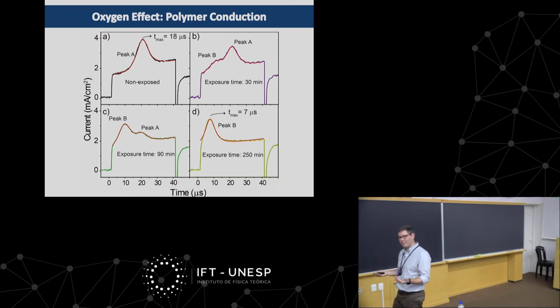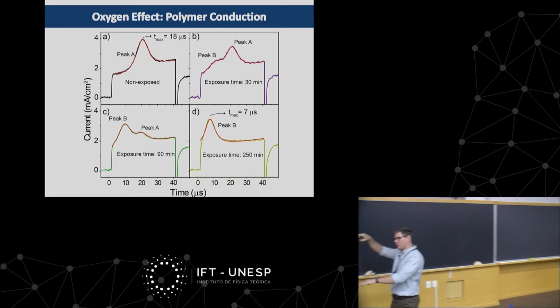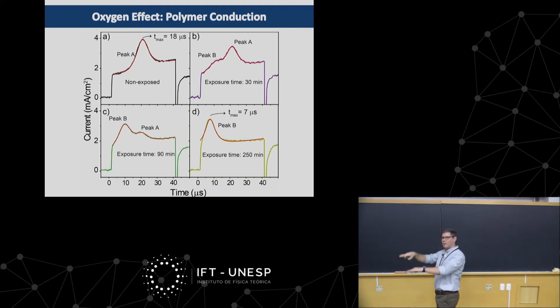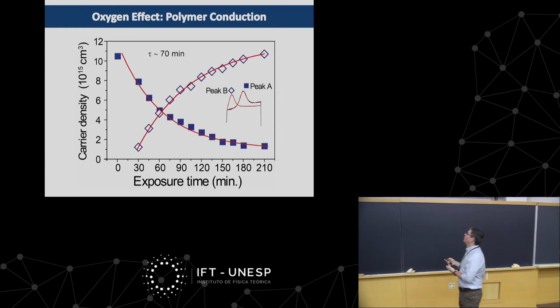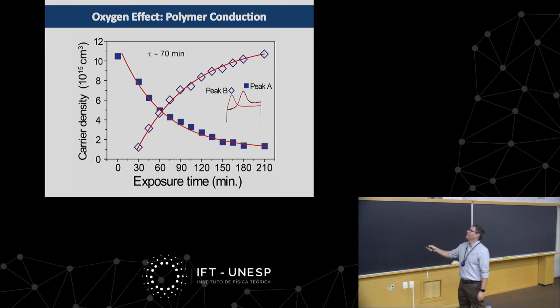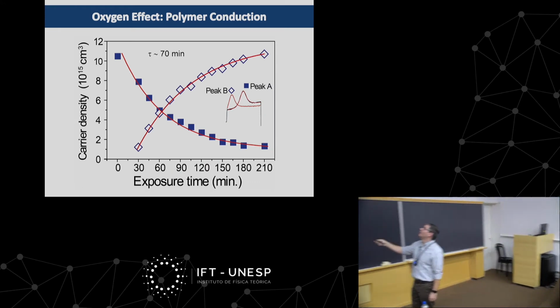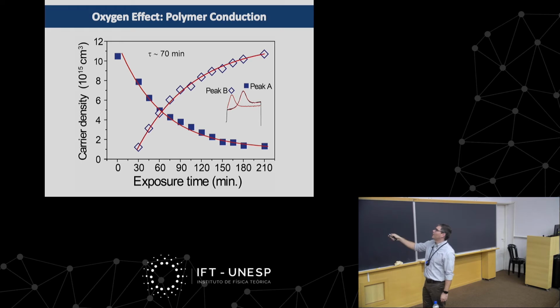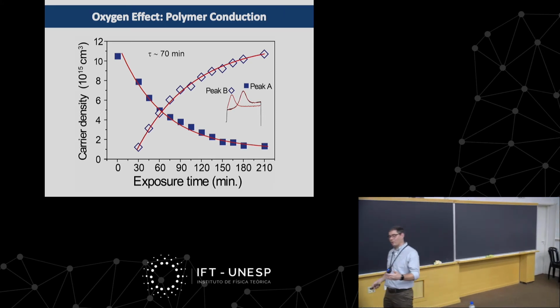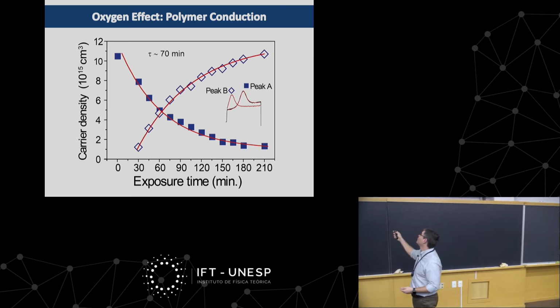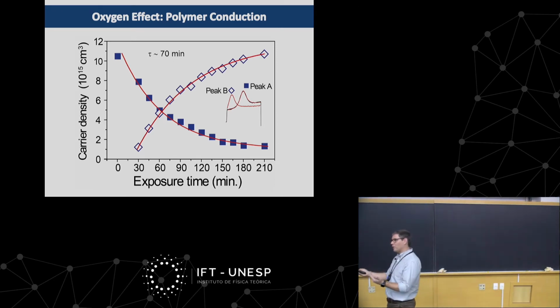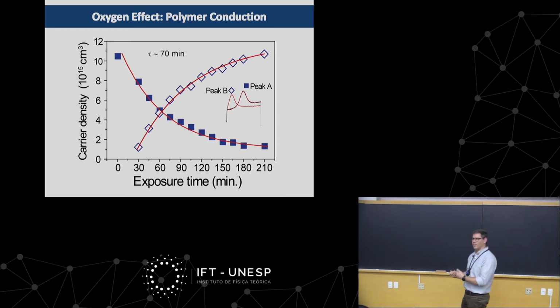And you see that the rate seems to be very similar. One actually decays at the same rate that the other one appears. And we actually measure the rate. So this is the charge density of peak A and peak B. Peak A decays, peak B rises, and they have a very similar recovery constant, about 70 minutes. One dies and the other recovers. So you can really see that one is dying at the expense of the other.